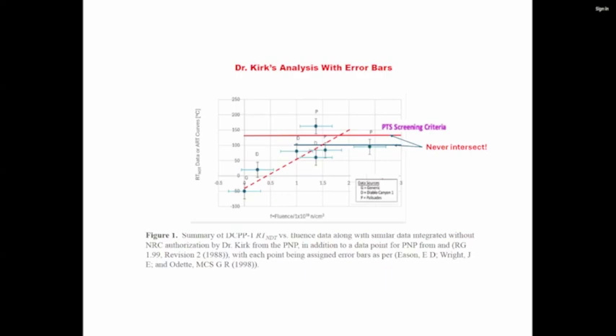And as you can see, if I draw a straight line through the data points with the error bars, which, by the way, are defined by Eason et al., so they're not invented by me, they're actually based on hard data, the intersection occurs somewhere between about 1.2 and 2.2 to 2.4 times 10 to the 19 neutrons per centimeter squared. On the other hand, if you were to draw a line through the two Palisades data points that he used, you draw a line that is essentially parallel to the PTS screening criteria, and these curves never intersect. And so what that means is the reactor could keep operating forever without running into a problem.